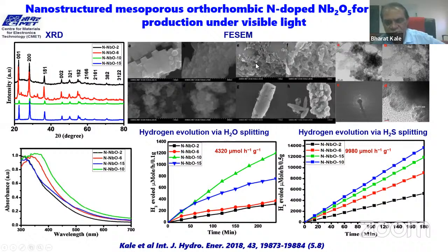And the beauty of this nitrogen doping is that whenever we dope with nitrogen, we found that there is a modification of the surface, meaning the surface becomes a little porous, and that helps a lot for the absorption of light as well as contact with water. So that helps a lot in enhancing the hydrogen evolution. Like when we did water splitting, we got almost 4,320 micromole. With H2S it is much larger, 9,980. As I told you, thermodynamics for water splitting and thermodynamics for H2S splitting are entirely different.